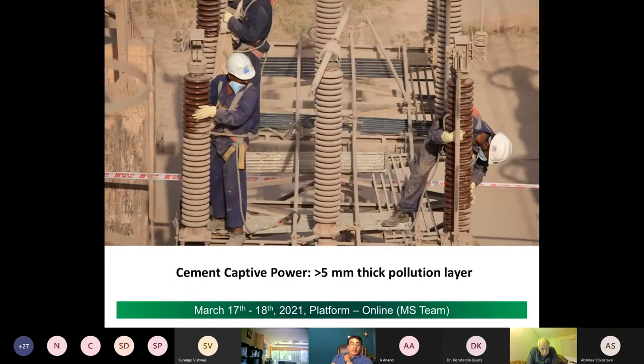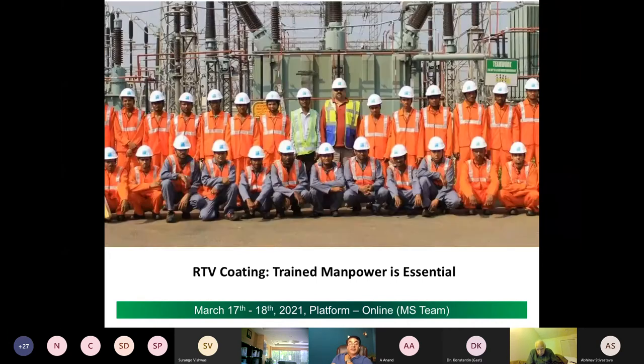Here is cement in a captive power plant. You can see there is 5 mm of pollutant layer, which is a major issue for hydrophobicity to transfer. But you can see here they're cleaning the layers of limestone-related mud off the insulator before the coating. Even here, it has been used for many, many years, no failure.